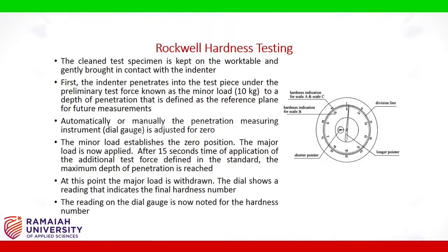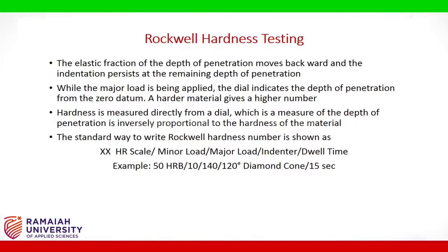After 15 seconds of application of the additional test force defined in the standard, the maximum depth of penetration is reached. At this point, the major load is withdrawn. The dial shows a reading that indicates the final hardness number. The reading on the dial gauge is now noted for the hardness number. The elastic fraction of the depth of penetration moves backward and the indentation persists at the remaining depth of penetration. While the major load is being applied, the dial indicates the depth of penetration from the 0 datum. A harder material gives a higher number. Hardness is measured directly from a dial, and the depth of penetration is inversely proportional to the hardness of the material.